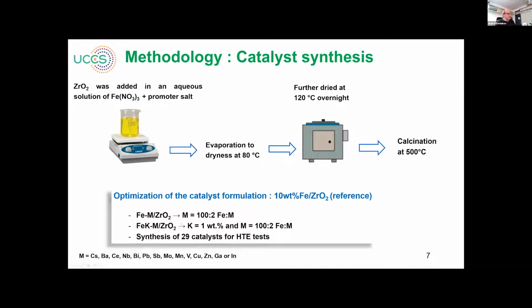We also found very fast that potassium is a very important promoter for all catalysts; I will show the results on the next slides. After optimization, we found that the best amount of potassium in the catalyst should be 1%. So this is a catalyst which doesn't contain potassium, only different elements, where the ratio of iron to promoter is 50. And we also studied a series of promoters with 1% of potassium, with the ratio of 50. So 29 catalysts were tested here.